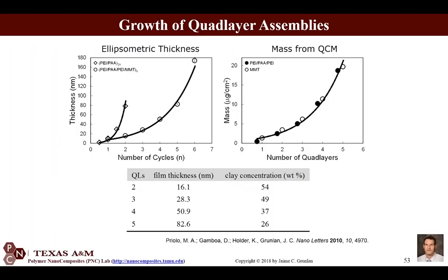And so anyway, when we look at the growth, which I can use ellipsometry to measure the film thickness because these are transparent films, if I deposit it on a silicon wafer, you can see that the growth is very exponential for this system. If I only looked at polyethyleneimine and polyacrylic acid, it's actually even more exponential because those are 2 weak polyelectrolytes that are highly interdiffusing with each subsequent layer deposition. The clay slows that process down to some extent, but you're still getting some interdiffusion and therefore what sometimes is known as exponential growth. So you can see how film thickness is increasing and clay concentration then is decreasing because I'm getting more polymer between each of those clay layers.